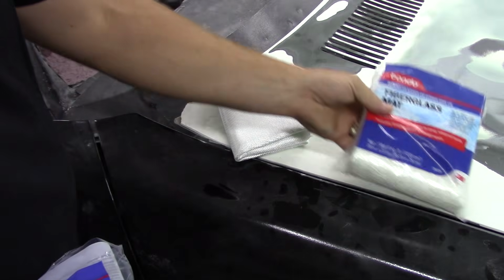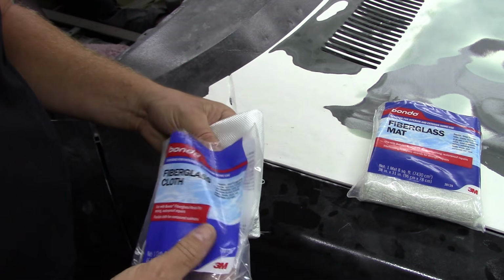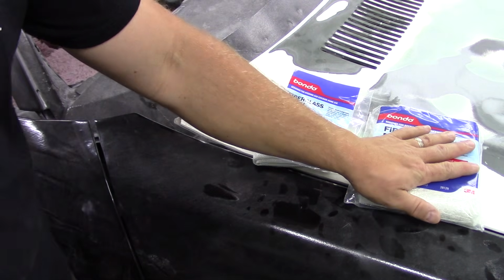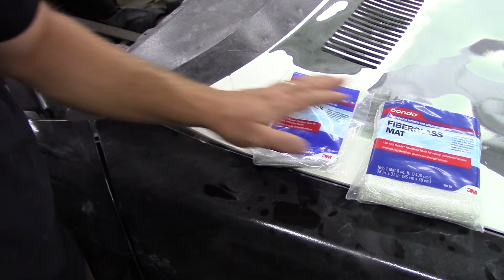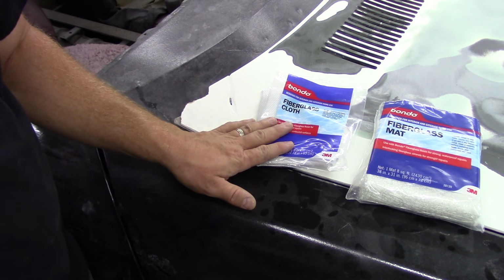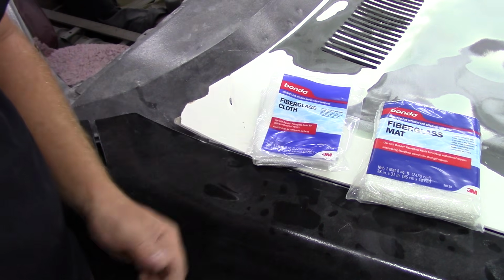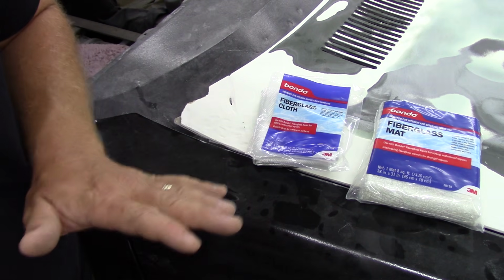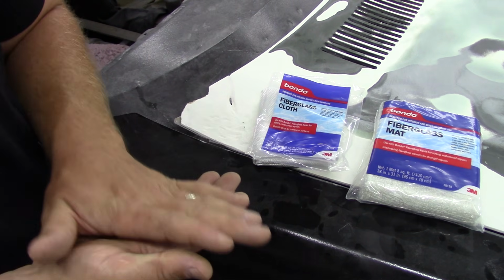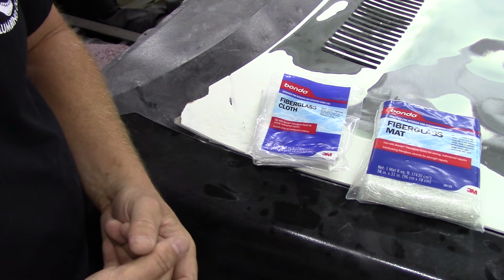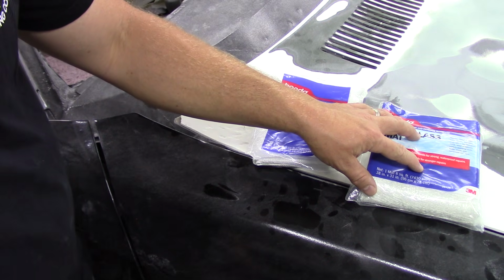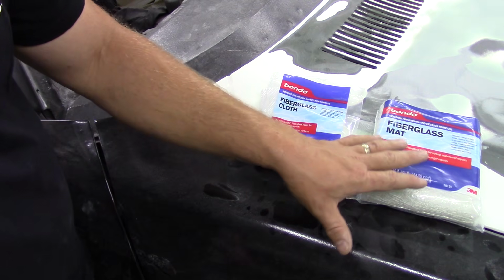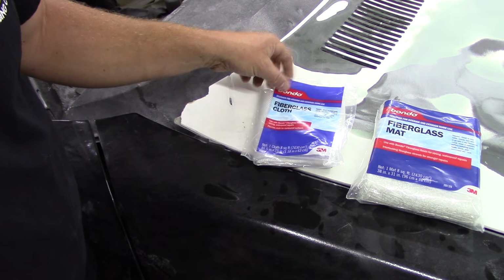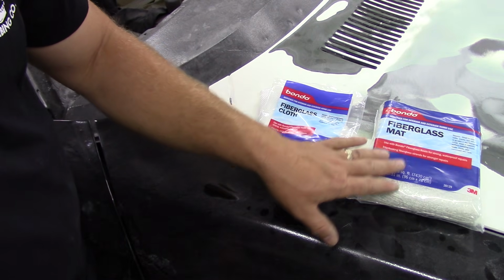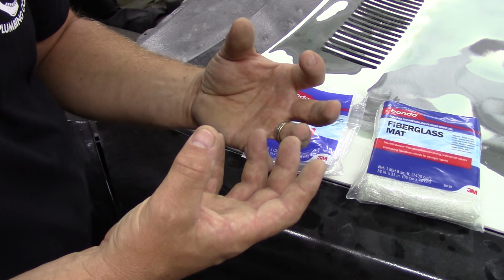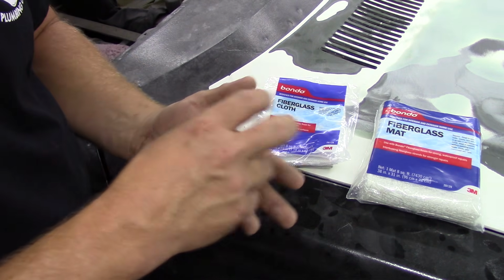So to make a correct repair that is both building and strong, I'm going to use a layer of matting followed by a layer of cloth, another layer of matting, and another layer of cloth, which essentially is what that biaxial fiberglass matting and cloth does, because it has the cloth together with the matting stitched in. So using the appropriate resin that will actually melt the styrene in here, for my SMC repairs, I will alternate matting and cloth, with the last layer possibly being the matting, because from what I'm reading, the matting will not print through your primer, whereas sometimes the cloth, you'll actually see that pattern.